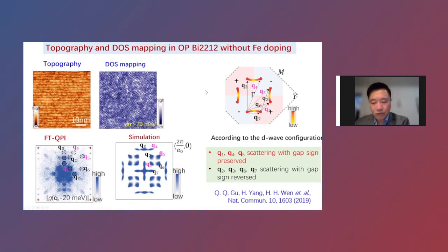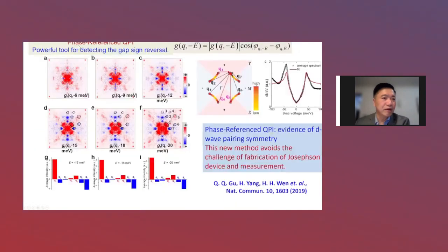Then we use the so-called phase referenced quasi-particle interference technique. This is a new technique. Then you can clearly show which ones are the scattering between the same sign and which ones are the opposite sign. Okay, we found that three have the same sign and four have the opposite sign. So this is a new technique to show the evidence of d-wave pairing in the cuprate. And this new method avoids the challenge of fabricating the Josephson device and the measurement, which is normally very difficult for checking the pairing symmetry.